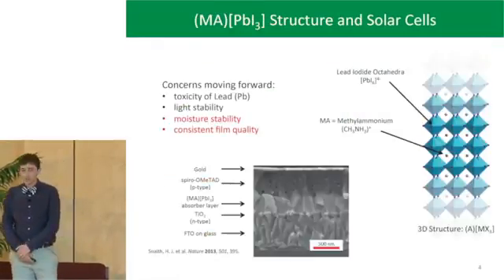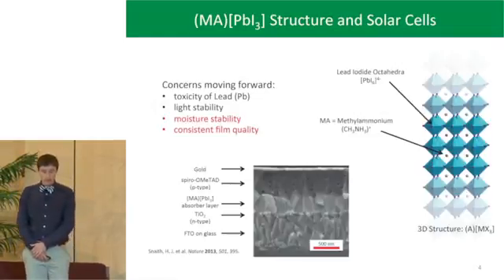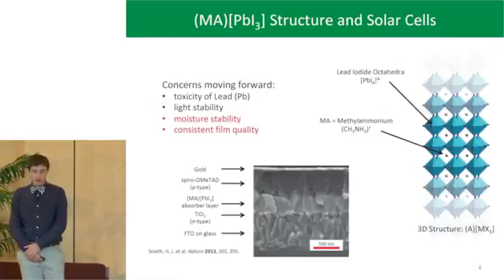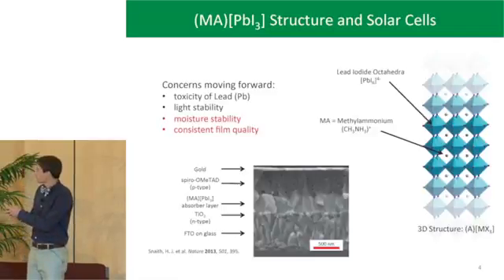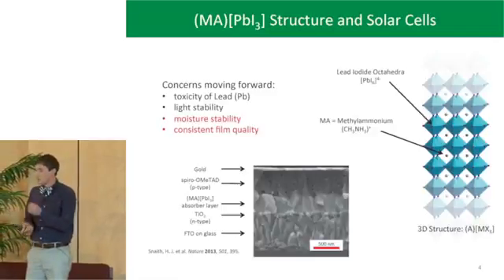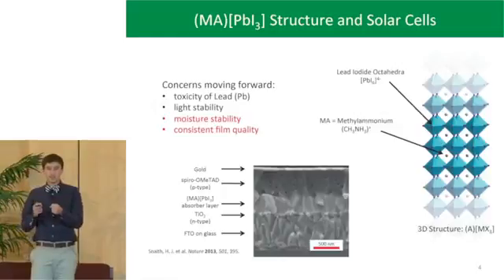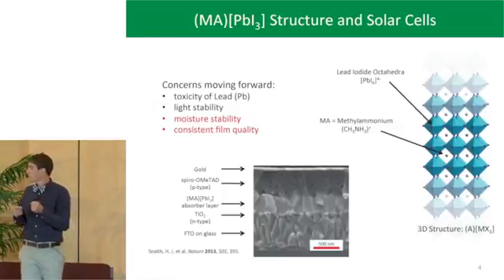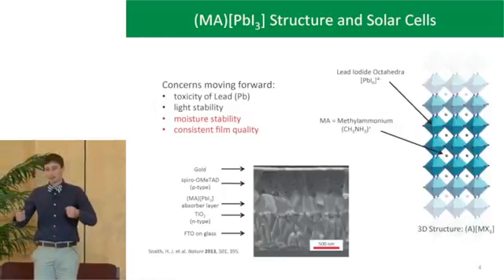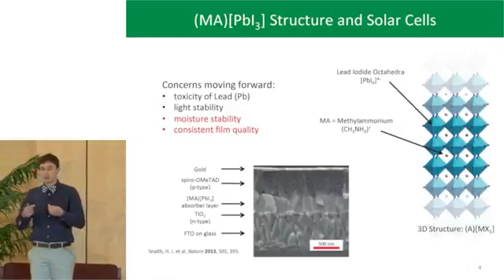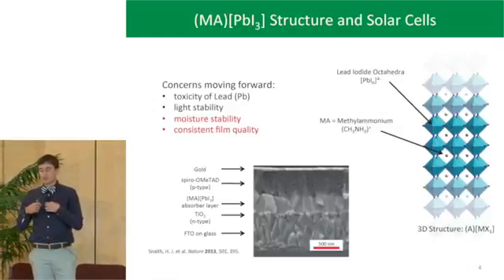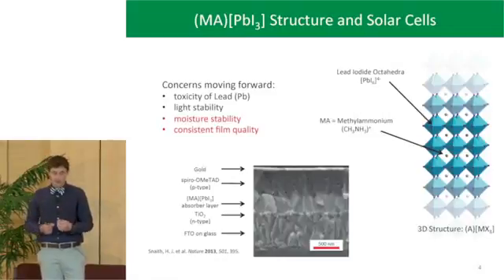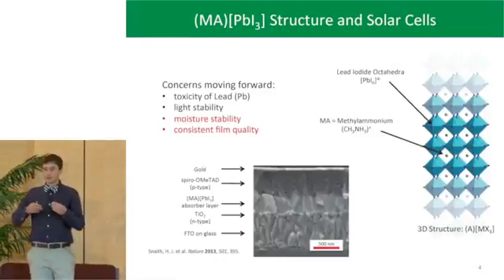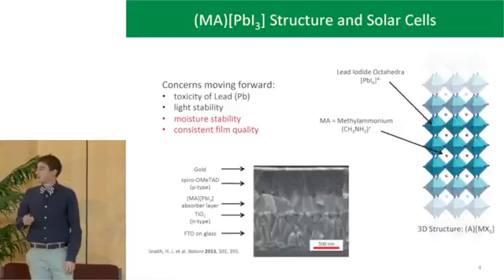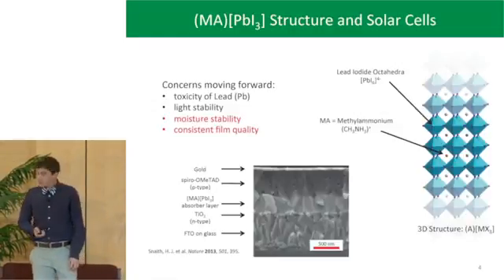So this is a perovskite structure. In this case, we're using lead iodide octahedra. So there's a lead in the center of this octahedron with 6 iodides around it. And each adjacent lead will share 1 iodide, which is the corner of those octahedra. That's why we say it's corner sharing octahedra. And then this will form a three-dimensional framework in all directions, and it's negatively charged. So to balance that charge, you need a methylammonium cation that resides in the cavity.